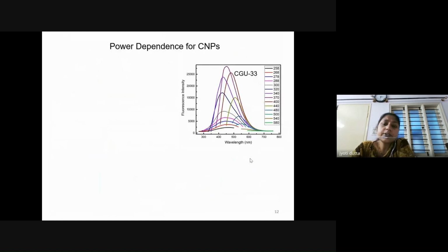So we checked whether the contribution is because of one photon or two photon or multiphoton fluorescence. So we first looked into the linear fluorescence profile of these carbonaceous nanoparticles, and we observed that all these nanoparticles are not showing any fluorescence at 570 nanometer, and there is no emission at 570 nanometer. So this ensures that it will not be a fluorescence due to a linear fluorescence property. Definitely it should involve multiple photons for the fluorescence property.